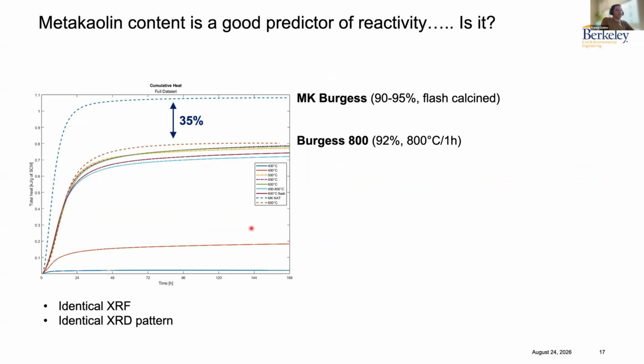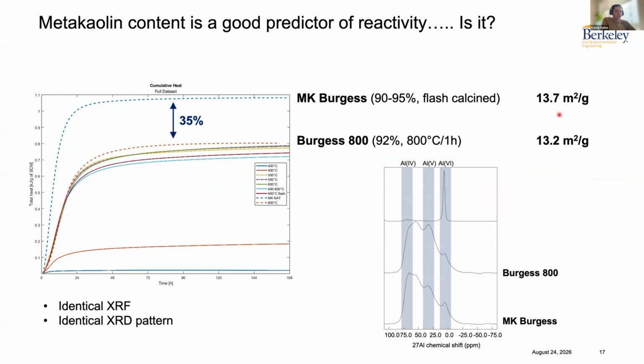However, they exhibit a 35% difference in the reactivity. And let's go back again. Surface properties matter. What the XRF and the XRD pattern are telling me is a little bit more of an idea of what's going on in the bulk or on the close surface semi-bulk status. However, there may be differences here that these techniques are not capturing that have to explain this 35% difference in reactivity. It's clearly not a surface area difference as we see here measured by BET, nor something that we can detect by solid state NMR either.